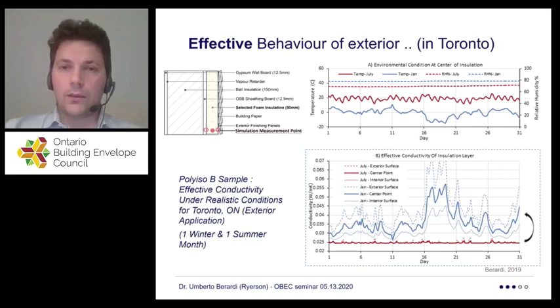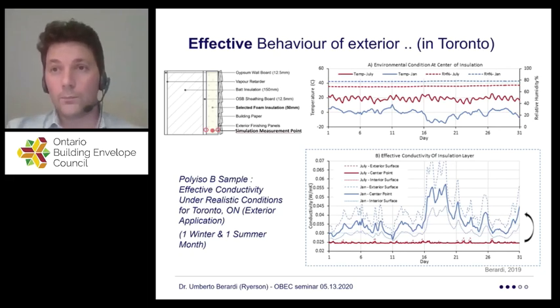Now, to give you the sense of what's happening, you can probably see there is a continuous blue line. That's the thermal conductivity of material in the center. And the two dotted lines above and below are the thermal conductivity of the two circles that you find, more exterior towards the sheeting or more towards the interior side of the wall. So this gives you the fluctuation of the thermal conductivity across the entire thickness of this foam.